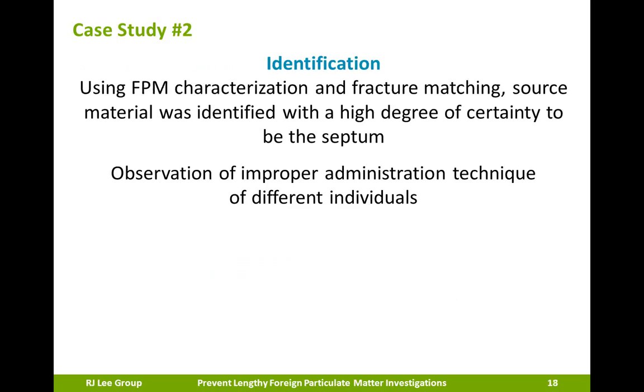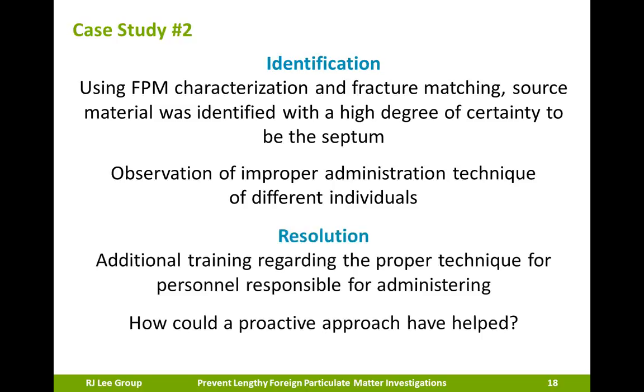The combination of the forensic characterization then with the fracture matching allowed a conclusion with a high degree of certainty that the gray particle sourced from the septum. And we presented these results to the manufacturer, who immediately initiated an observation investigation for the administration technique of the product. To resolve this issue then, additional training on proper administration technique was required. So the problem was solved, but it was retroactive versus proactive.